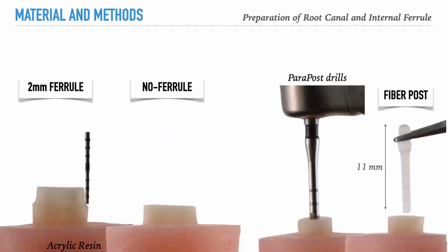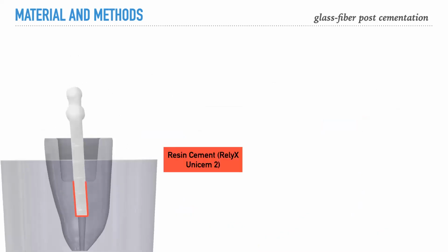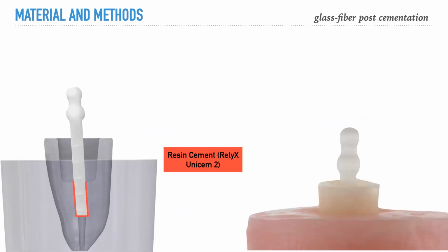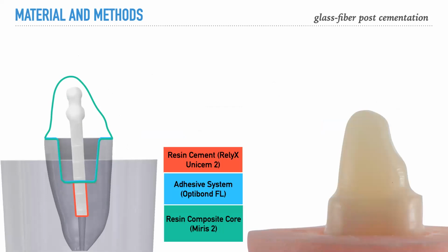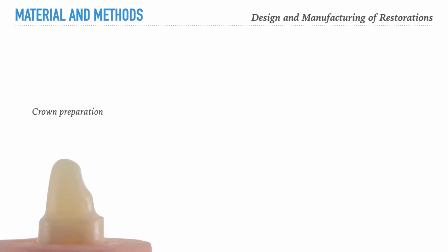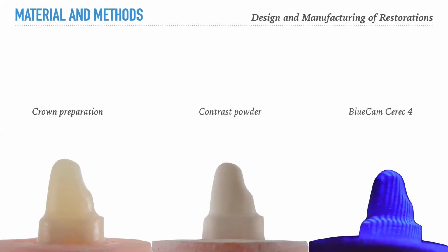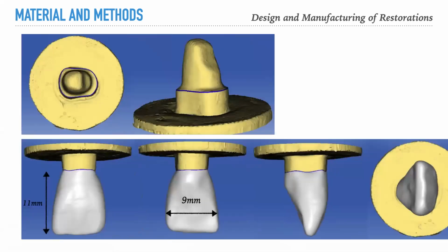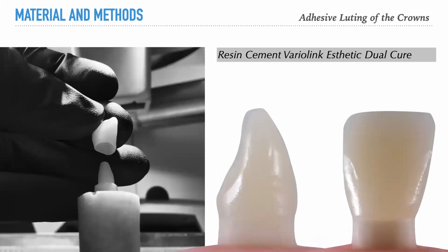So the roots were prepared to receive a fiber post or to receive a so-called internal ferrule. That was a preparation inside the root to receive the core buildup. The posts were cemented with dual cure resin cement, and then in this internal preparation, we applied the adhesive system and built the core with a regular composite resin. After that, the samples were prepared to receive a full crown that was designed and manufactured using the Cerec system. And here is the size of all crowns that were milled using lithium disilicate blocks. For the cementation, we used the resin cement Variolink Esthetic dual cure. And here we have the pictures of our final samples.